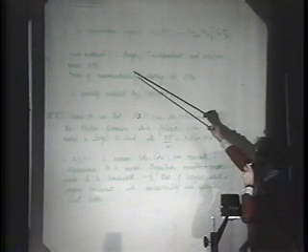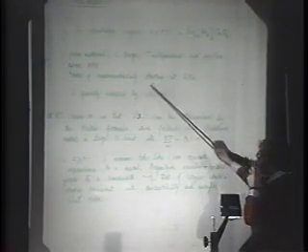So in conclusion, in the low concentration regime, pure material, thermopower is very large, T independent and positive. This is all above 80 K. Below 80 K there are traces of superconductivity. S is quickly reduced by doping.